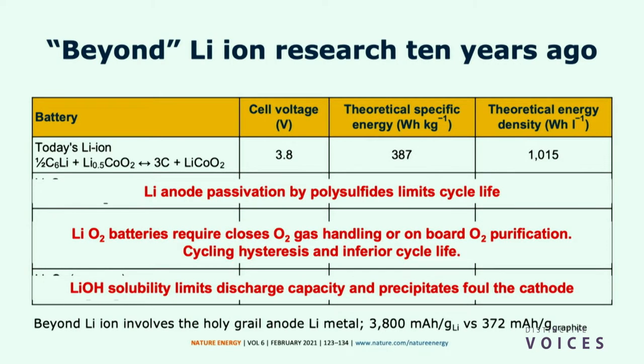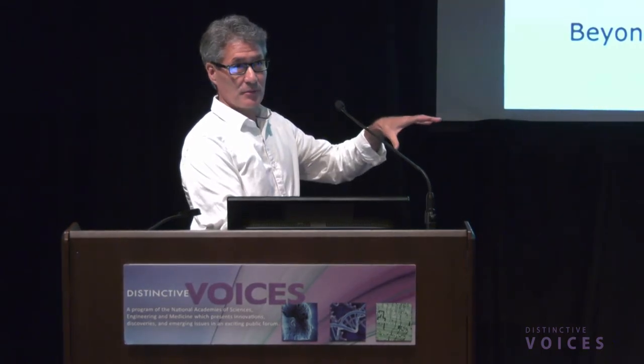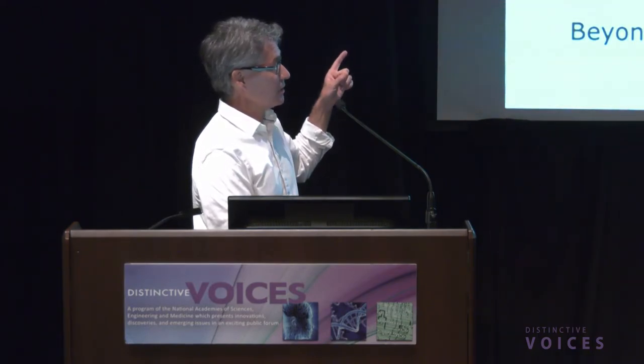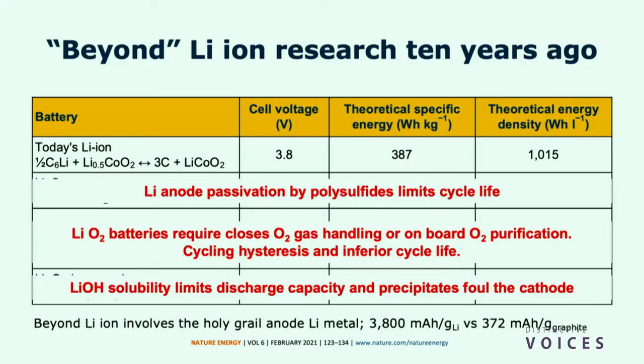But one thing that they did have in common, instead of graphite, which lithium ion uses, six carbon atoms for every lithium atom, the holy grail anode is what all these three electrochemical systems relied on, pure metallic lithium. And if you look at the capacity, again in charge, milliampere hours per gram of lithium, there's a tenfold increase, or a factor of 10, penalty when you have to add six carbon atoms for every lithium atom, when you go from lithium metal, the holy grail, to graphite.